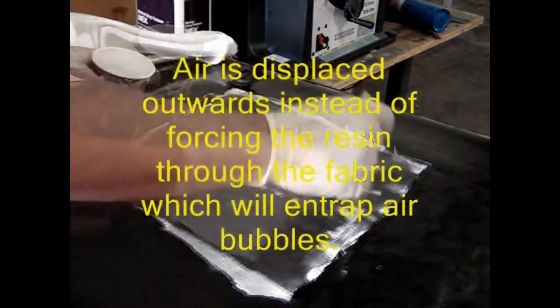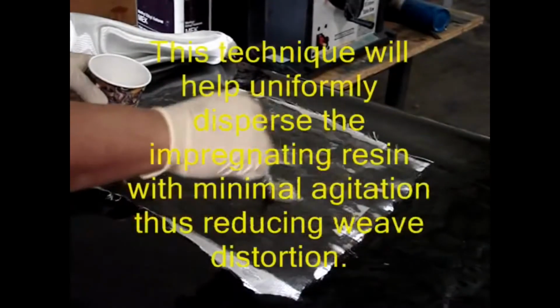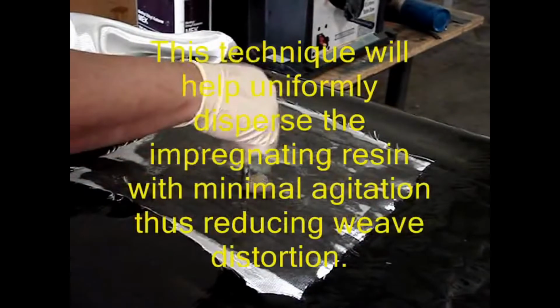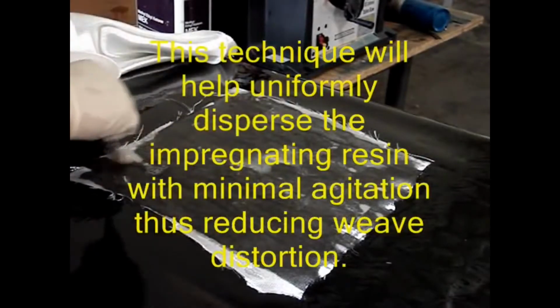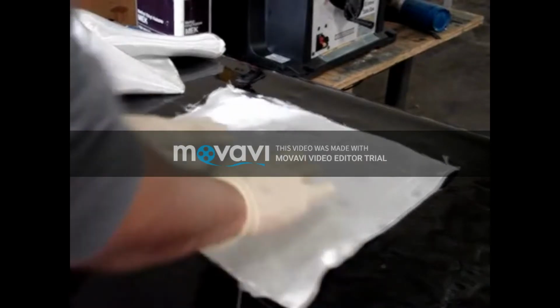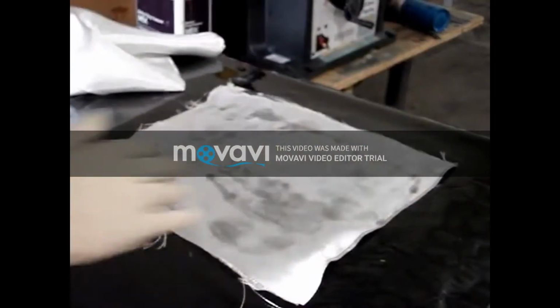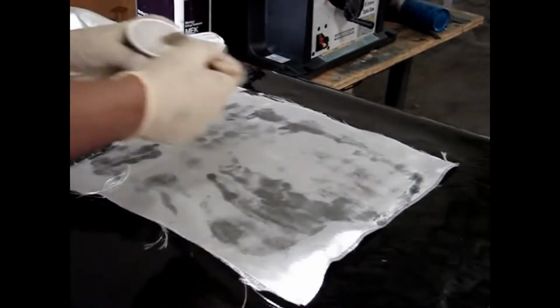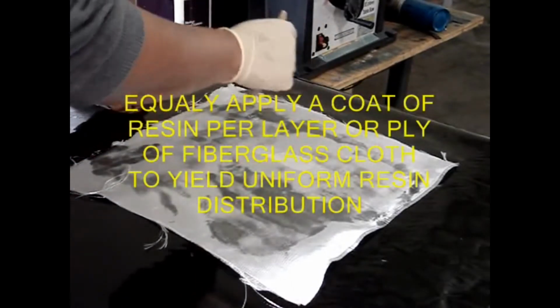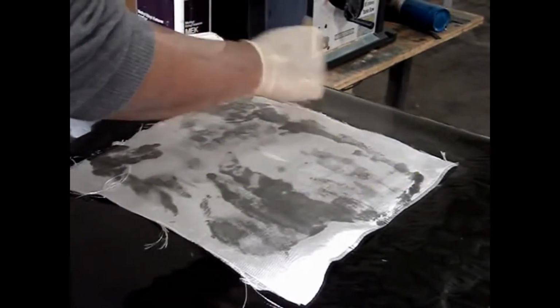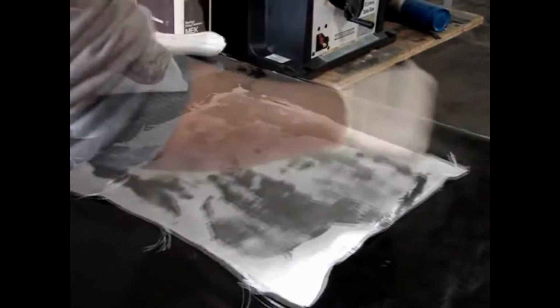Next, air is displaced outward instead of forcing the resin through the fabric, which would entrap air bubbles. This technique will help uniformly disperse the impregnating resin with minimal agitation, thus reducing weave distortion. Next, we have to equally apply a coat of resin per layer or ply of fiberglass cloth to yield uniform resin distribution.